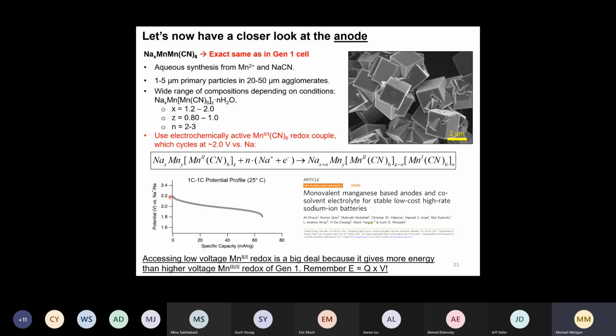And you see, from about 2.2 volts to 1.8 volts. So an average voltage of about 2 volts, you can reversibly cycle about 70 milliamp hours per gram worth of sodium. And the way you do this is written in this equation here. So you start off with your sodium manganese hexacyanomanganate material. They leave out the water here for clarity. And then you add N sodium atoms to your structure. So you end up with NaX plus N.